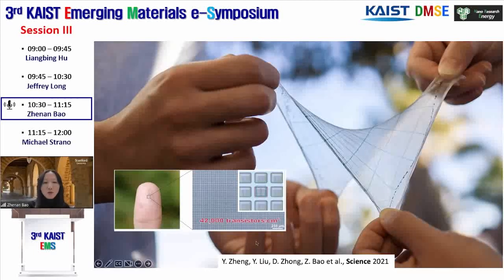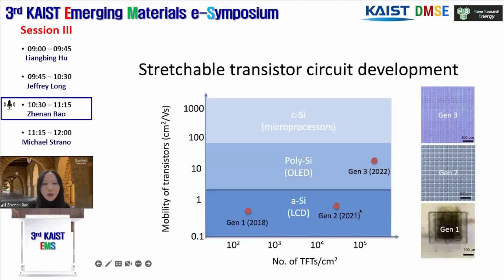But use direct photo patterning to make these integrated circuits, we can significantly increase the density of the circuits as well as the yield for producing such devices, which is important to build more complex integrated circuits. So with such development, we were able to much increase the density of the transistors per centimeter square, as well as the charge carrier mobility.